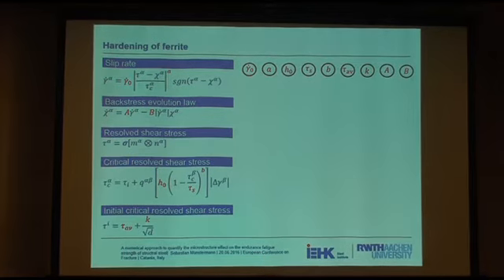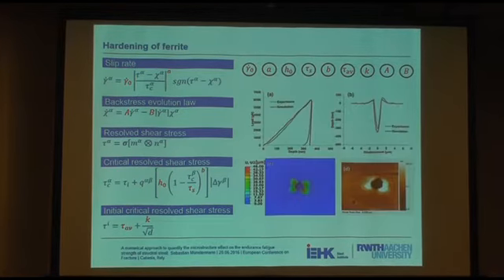Okay, now we've got our microstructure models and we need to describe the constitutive behavior of the individual phases. We've observed in some experimental investigations that the pearlitic phase was not that important because we saw that the incubation happens in the ferritic phase. Therefore, we cared for this quite a lot and we have used a crystal plasticity model to express the hardening behavior of the ferritic phase. It's a phenomenological model that does not consider strain gradients, but at least it considers kinematic hardening. So it's a combined kinematic isotropic hardening model that we have used.